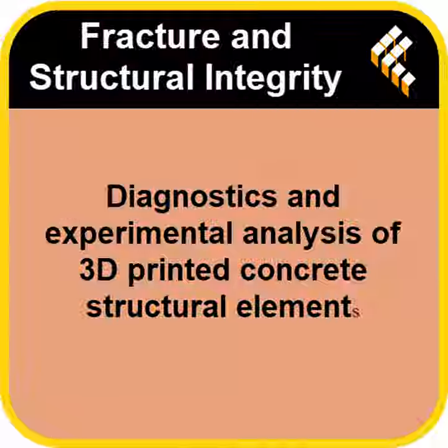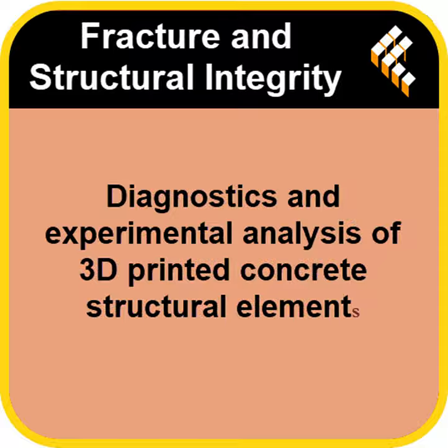We need that diagnostic toolkit you mentioned, non-destructive methods. We do, and the study looked right into that. They found some really clear correlations with physical properties you can measure pretty easily. Like density? Like bulk density. Higher density, up to about 2,250 kilograms per cubic meter, almost always correlated with better flexural strength.